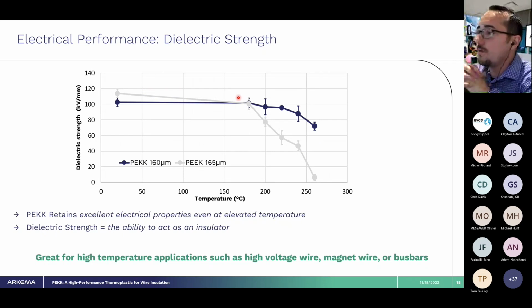And then to take that a step further, the dielectric strength. Obviously a higher dielectric strength here is better, versus a low dielectric constant being better. You all know that probably better than I do. Again, we're comparing up through elevated temperatures, the PEKK material to a common industry material. The thickness for these would be about 160 microns. What you can see is the same pattern we've seen consistently throughout a lot of the performance data. As we approach 150, 160 degrees C, the performance of the PEKK continues to outperform the PEEK material due to the higher thermal characteristics of the PEKK. So our dielectric strength out through 100 to 250 degrees C is clearly much higher than PEEK will be at these temperatures.